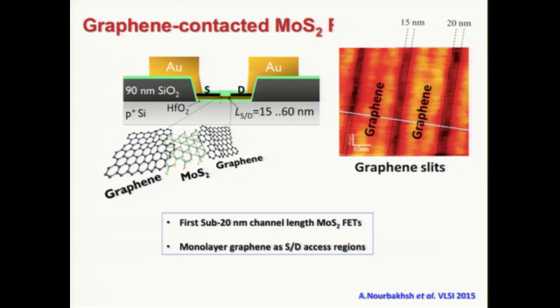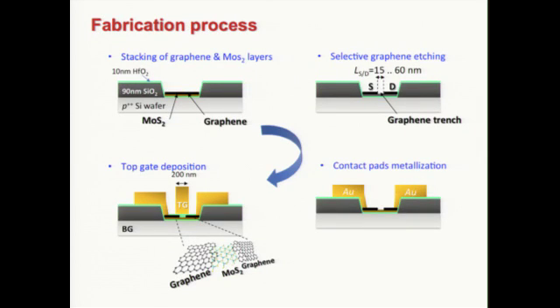So this is the device structure that we designed. We have 2 layers of graphene as the source and drain. We have a trench here that defines the channel length. You see it here in these AFM images. This is a typical process flow. We first stack a layer of graphene and molybdenum disulfide on a p-type silicon wafer with about 10 nanometer hafnium oxide as the gate dielectric. Then we selectively etch graphene to define the channel. Finally, we put down the measurement pads, gold layers. And if we need to improve the gate electrostatics, we can build a top gate electrode as well. So we deposit another layer of hafnium oxide and a top gate metal.